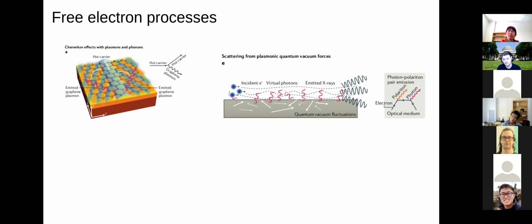Now, you could think about sending an electron through a medium with an index of refraction and asking what the two photon pair generation would be at higher frequencies, but this would be absurdly low. And so in this case, the absurdly low nature of this process gets helped by the fact that you have this sub-wavelength plasmon as part of the process, so that the generation of the ultraviolet or X-ray frequency photon, which is probably what you care about, piggybacks on the efficiency of this process. And the amount that you get out theoretically, it's not a lot, but it's way more than you would expect normally, and it's maybe detectable.